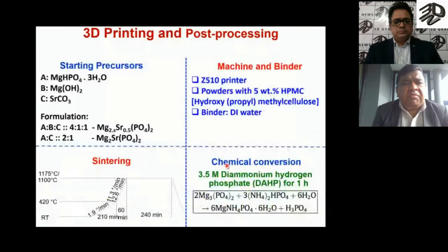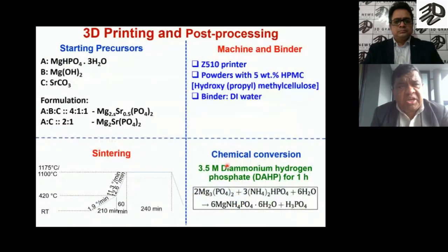Right. So if you look at this, how we make these materials is important, because these materials can be very good in terms of biodegradation property and so on. So we started with precursors like magnesium and strontium precursors. Then we used powders with 5% HPMC binder, 5% HPMC additives, and the binder used was simple deionized water. We have used two post-processing approaches: one is sintering and one is chemical conversion. And in the sintering and chemical conversion, we have seen the impact on these materials.